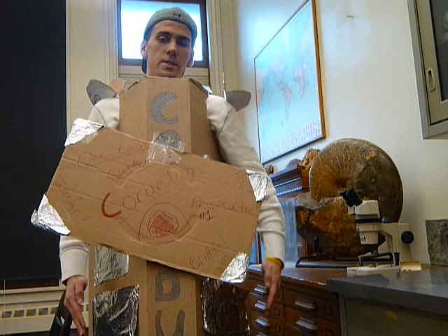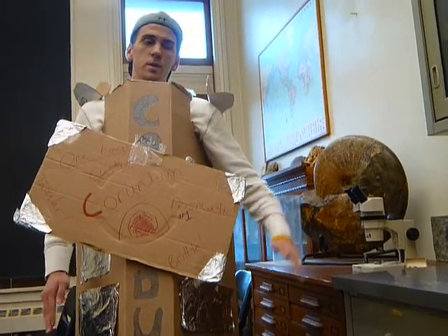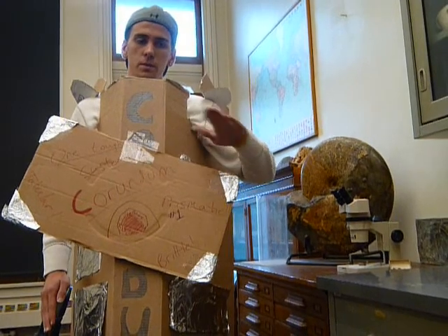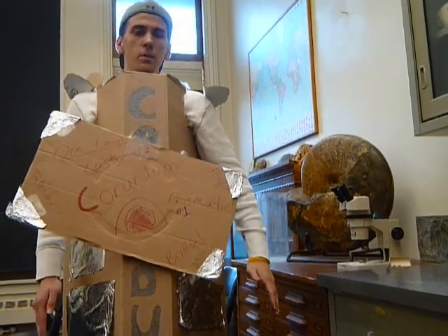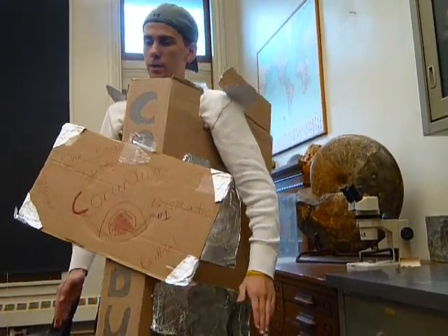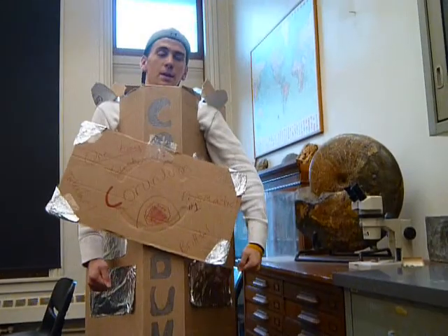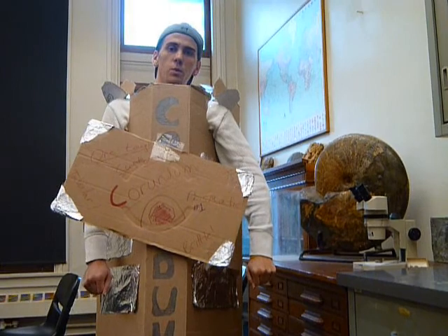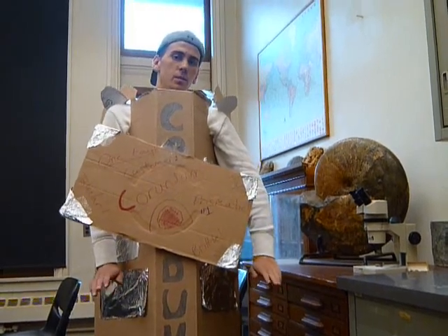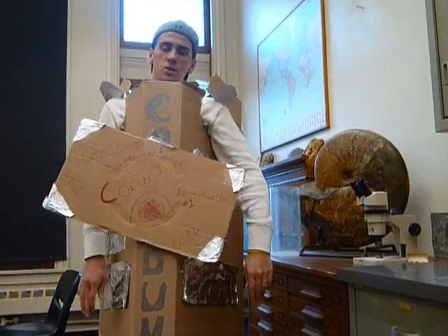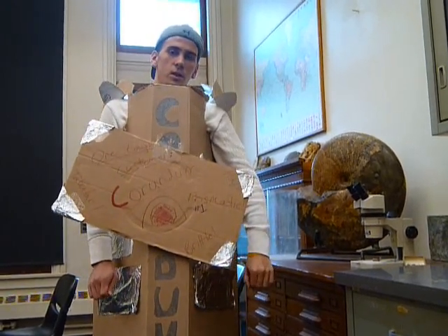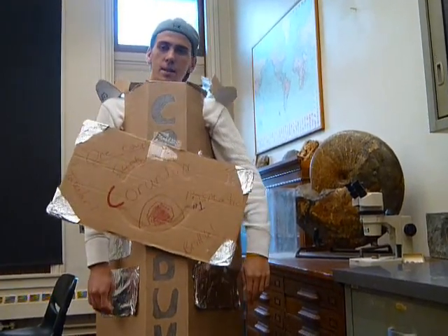Corundum also has a basal parting, which means it parts along the middle plane of its unit cell. It's a very flat plane. It also has a rhombohedral parting. Corundum has very common twinning on the {1011} in the hexagonal Miller-Bravais notation, and very uncommon penetration twinning, if you all know what that is.